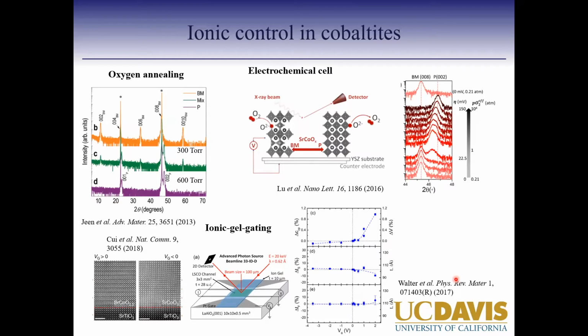You can control the oxygen ion content with a variety of methods. Oxygen annealing is one example, where you start with, let's say, a brownmillerite phase, and then anneal in oxygen. I'll talk about what brownmillerite actually means, but for now, it's an oxygen deficient phase, with oxygen vacancies which get ordered in the system. As you anneal it more and more in oxygen, you can actually change it to the perovskite phase.